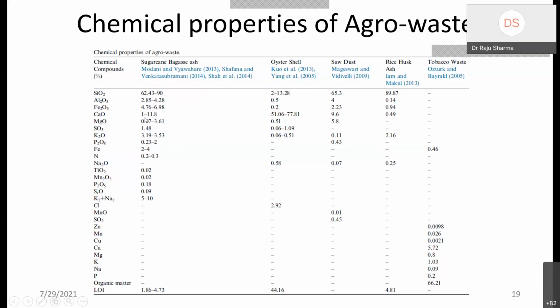This calcium is very high, because if the calcium is 1%, the results will be different than with calcium which is 10 or 11%, right? So some people are getting different results than other researchers because of this difference in the chemical composition. Now, if you look into the oyster shell, you can look into that.